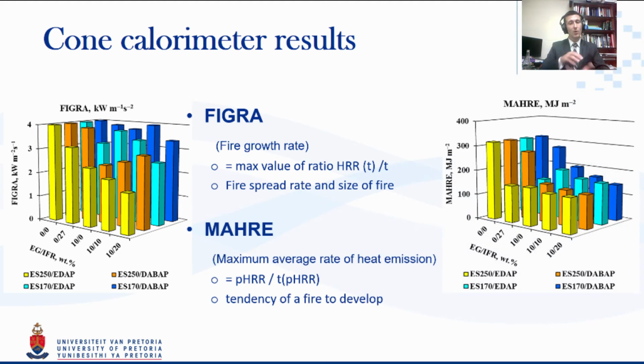Now, on the MAHRE, we look at the tendency of a fire to develop. So it gives an indication of how quickly a fire will develop into a fully developed fire. So it is somewhat related to the heat release rate. What it actually is is the maximum average rate of heat emission. So MAHRE is the peak value of the ratio between the heat release rate over the time until it reaches that point. But what we found here, which was really great again, was that our combinations again exceeded our materials on their own.